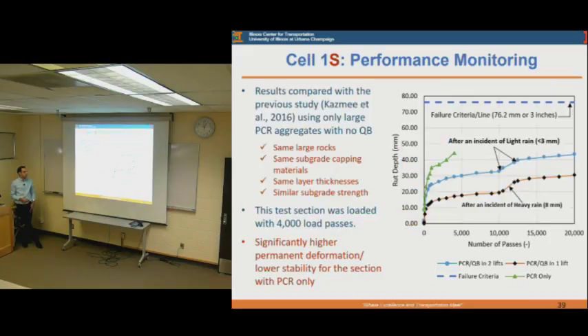This slide shows a comparison between the test sections that are constructed with the primary crusher runs and the quarry byproducts in one lift, here, the lower one, in 2 lifts, as well as a previous study that used only the primary crusher runs without any quarry byproducts. And it was tested up to 4,000 cycles.